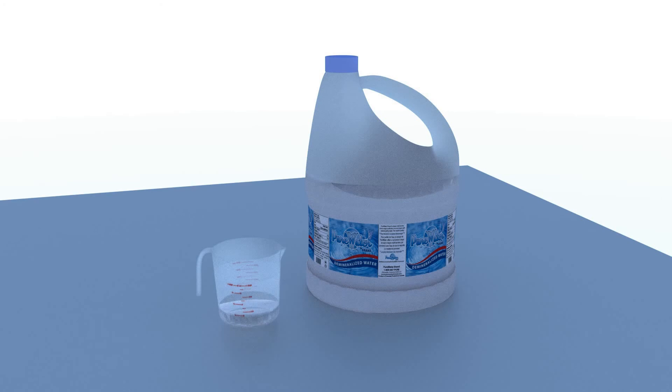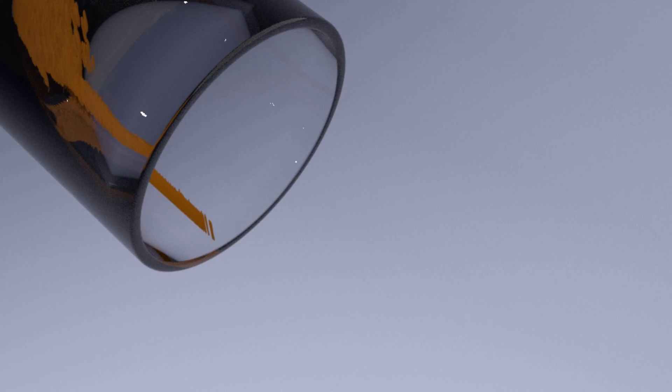Give the gold mud a final rinse with about a cup of distilled water. This rinse will wash away any minerals or other impurities that might be in your tap water. Before removing the gold from the chamber, give it a chance to dry thoroughly. When wet, the gold will stick to the sides of the container, making it difficult to remove. However, when dry as the Sahara, the gold will pour out like sand.